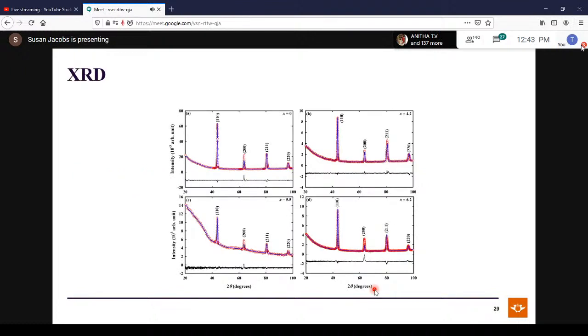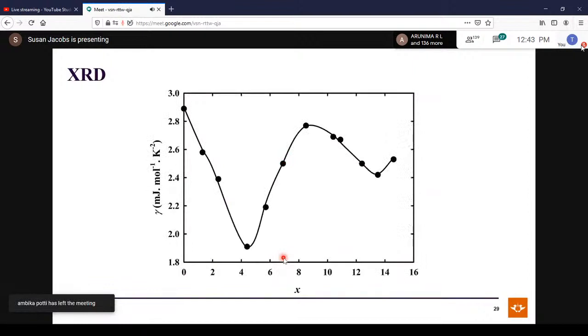So for neutron diffraction measurements, we made 4 samples. We chose 0% vanadium, 4.2% vanadium, 5.5% vanadium, and 6.2%. Why did we choose specifically these 4 concentrations? Well, if you remember the curve that I just showed you, we want to know what's happening here. So we made 4 samples in the vicinity of this minimum to investigate what exactly is happening in this curve.